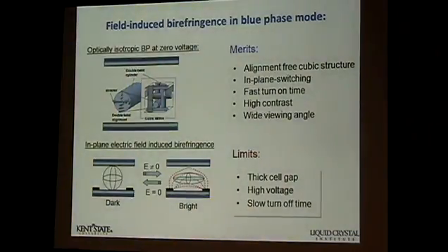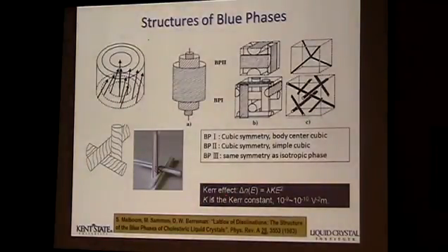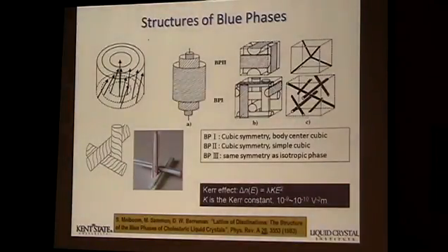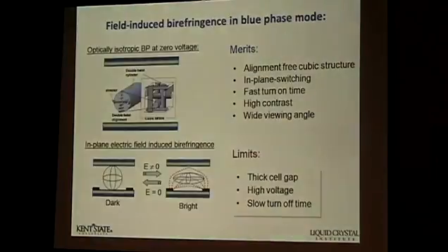So with this kind of condition, you need to optimize to maximize this electric field, because we just mentioned that the field-induced birefringence is proportional to the square of the applied field, right? So it's very important that you maximize that, so you get the maximum induced birefringence. Between the dark state and the bright state, with crossed polarizers and the dark state at zero voltage, you want to apply small fields, save your energy, but still induce the maximum contrast, and that's important for this factor. So optimizing the structural electrode properties is an important factor.